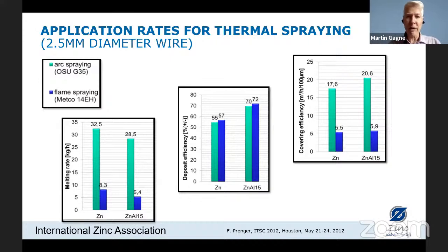Now, if we look in the center graph, the deposit efficiency, there are some particles that solidify before they impact the coating and will bounce off. So this also depends on the operator's skill, but this is less dependent on the spray technology, arc spray or flame spray, but more dependent on the alloy. And we seem to have better deposit efficiency with the zinc 15% aluminum alloy than we do with the pure zinc metal wire.